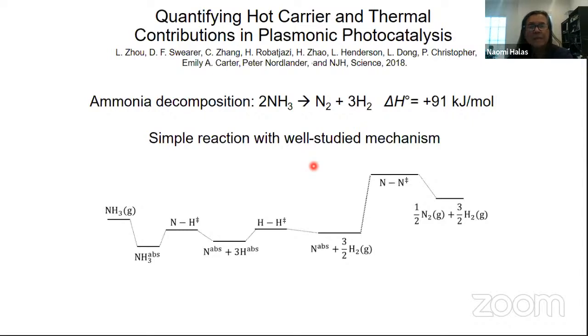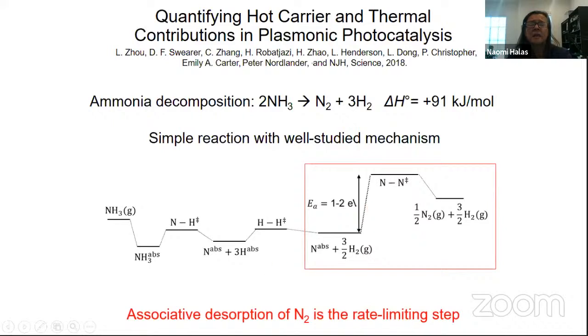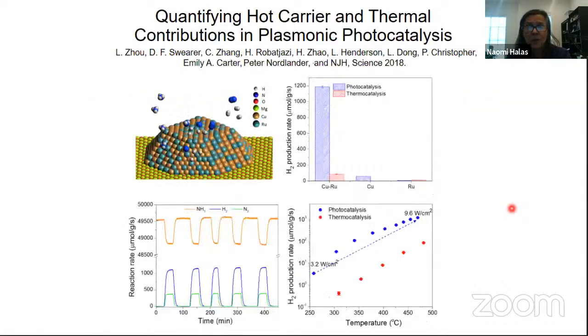And so we decided to study a very simple chemical reaction that's very well studied. It's the decomposition of ammonia. It's been studied by many people over many years. It's a very well-defined mechanism, and the rate limiting step is the associative desorption of N2. So once you have ammonia adsorbed onto a surface, you dissociate the hydrogen from the nitrogen, you leave the nitrogen on the surface, and then the barrier is related to the nitrogen atoms recombining with each other and then desorbing from the surface. So that's our standard understanding of the mechanism of ammonia decomposition, which, by the way, is a very important reaction, and I'll mention why in a moment.